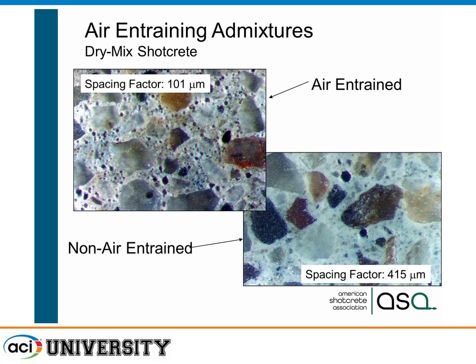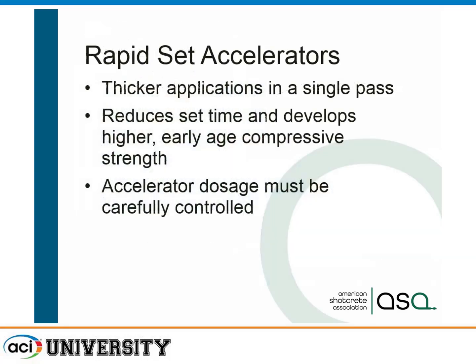We knock air out. And so we do tend, if you measured 7% at the truck as it came out of the truck, it may be 4% in place because what we do, we knock out the bigger entrapped air bubbles. We keep the little bubbles. Those have a lot of surface tension, but the big ones get knocked out. So we keep very good freeze-thaw durability, even though you do lose a little bit of air content.